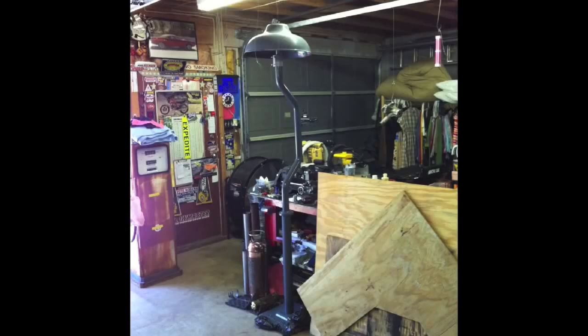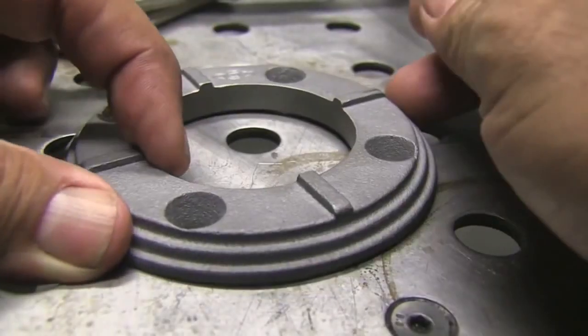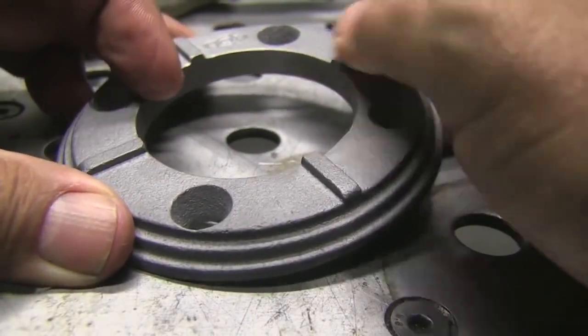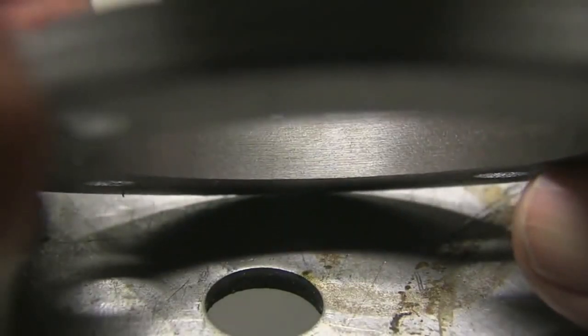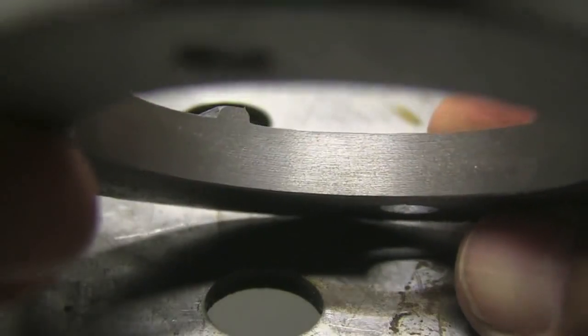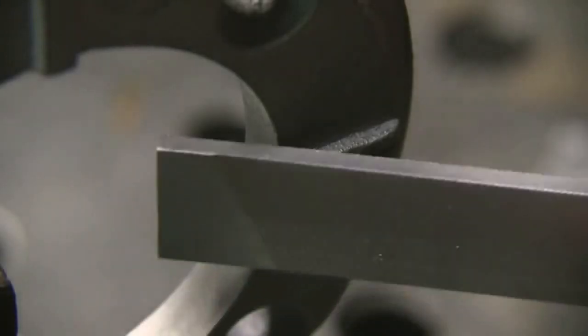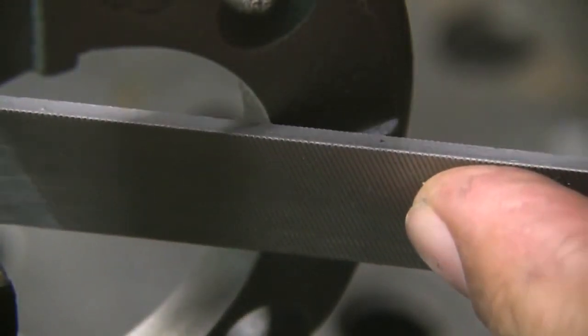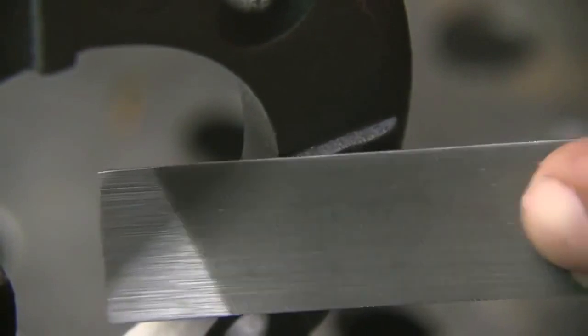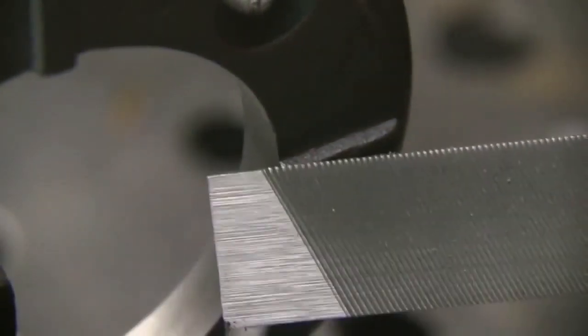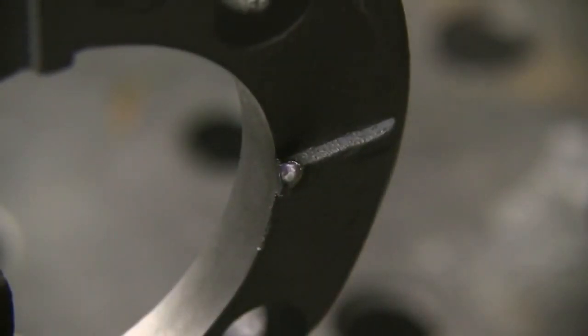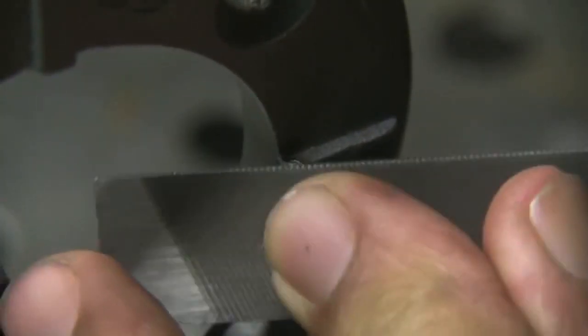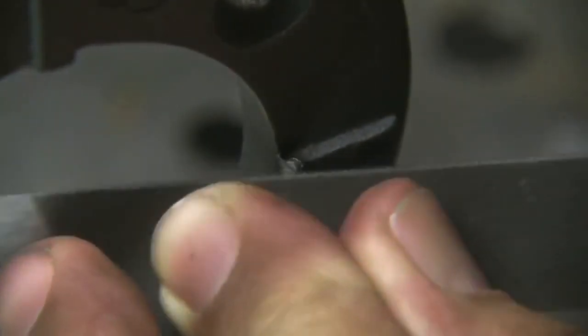Now I did this little job a while back for a guy he's restoring an old gas lamp here he gave me this cast iron flange at least he said he thought it was cast iron this is an original flange but we're welding it to 409 steel pipe so that's the only type material he could find that was the right diameter to slip in there and he even had to turn this on a lathe a little bit so what I do on a job like this I want to verify something's cast iron first I'll cut it with a file a little bit and see where I'm at see how easily it cuts with a file and then I'll pick a spot like that corner right there that won't hurt anything and then I will puddle it very quickly with a TIG torch and what that does is it heats it up past melting and then quenches it cools it really fast and if it's going to get hard that little weld right there will be hard as a BB.